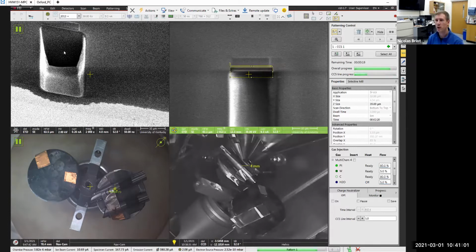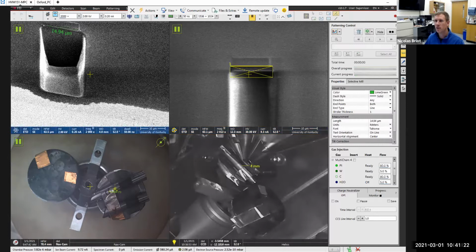Now you can really decide where to cut. But if you have a sample that's pretty uniform and you want to have a good idea of a wide region, so it's more representative, that other machine I talked to you about is going to be nice, because you're going to be able to do an analysis over 1 millimeter or more, which is going to be more representative than what I have right now, which is only a 15 microns wide region.